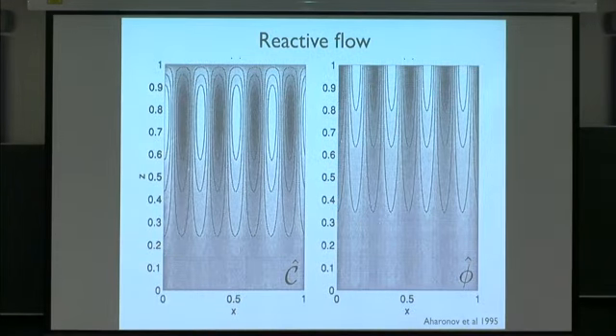as with the case of these shear instabilities, this process is unstable, and so where you start at the bottom of the domain with a uniform porosity, you can spontaneously produce localizations where melt will preferentially flow through and react in these channels where you have more melting, lower pressures, and convergence of melt streamlines. And diverge away from these regions that are more compacted in between. You can see that divergence of the solid phase where there's already more melt.